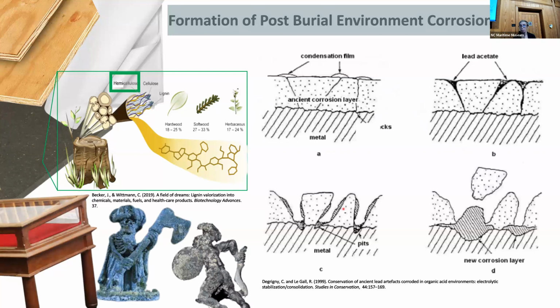And how that works, as you can see easily from this nice handy diagram, is you have your ancient corrosion layer. So you can take this as your passivating layer. This is that crust that I was talking about that is protecting that core metal. However, you start having organic acids build up in the environment. They're depositing on top of this layer and starting to build up, and then they start essentially eating away and dissolving that layer, creating little holes, and eventually creating these pits in the surface. So first of all, you lose a layer of material, but then you're also eating away into the material that was formerly being protected by this crust and creating more damage, both in the form of physical damage, loss of material, as well as what we call pitting corrosion.